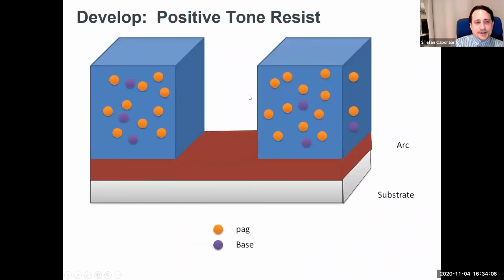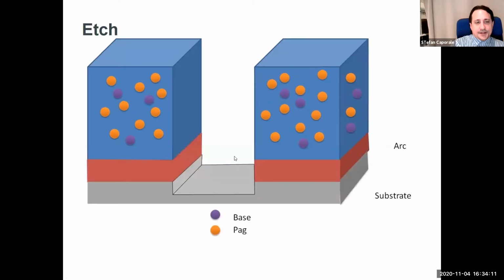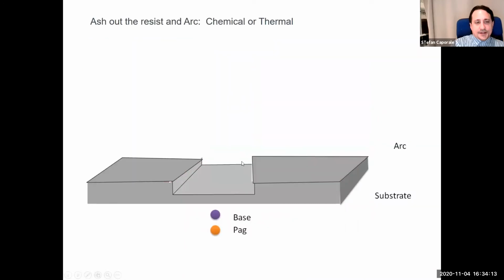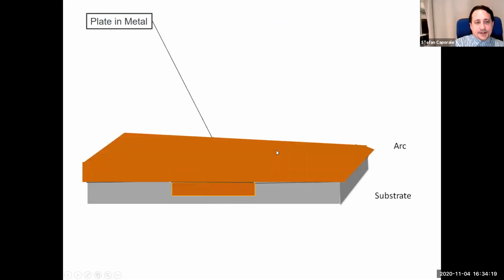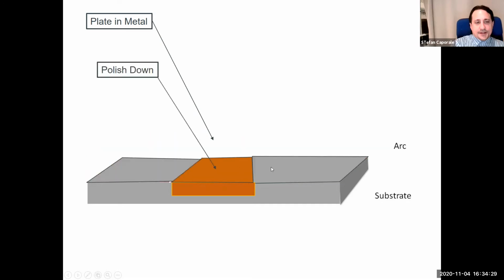After it's developed away, you have now your pattern transferred to your resist. You then etch that away, and then you would chemically remove your photoresist. Again, I'm not an artist. Then you would plate copper over the top of that, and you would get this. You would then normally end up overplating and get that completely over the resist. And then you polish that down, which is actually a separate product that DuPont makes as well, which are these large pads and chemical slurries that are used to polish these wafers down and to get the uniformity across here within an order of nanometers.